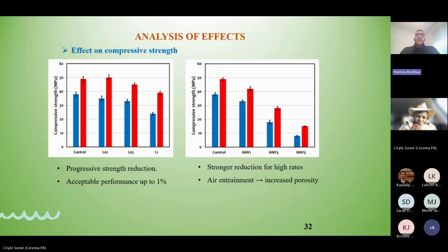And also, as we said before, the reason behind this decrease is not the same for lignin and oil. For lignin, it's a chemical effect, which is this delay of hydration, this complexation with the cement phases. But for the oil, it's different. It's a physical effect, which is introducing more air in cement paste and increasing the porosity of the cement paste, and then decreasing the compressive strength of cement paste.